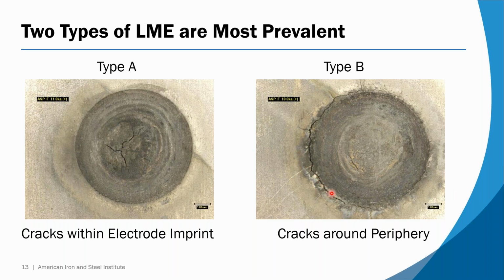Okay, you have these arms cracking radially, stemming off of the peripheral crack. That maybe is type B, I don't know, but its temperature is falling very quickly as you get further away, moving away from the nugget. This is molten metal underneath, and the temperature's falling like a rock as you get away from this. So the fact that this has a radial crack moving away means it's really susceptible at an extremely low temperature. That's the most egregious LME crack as far as saying you have a sensitive microstructure.